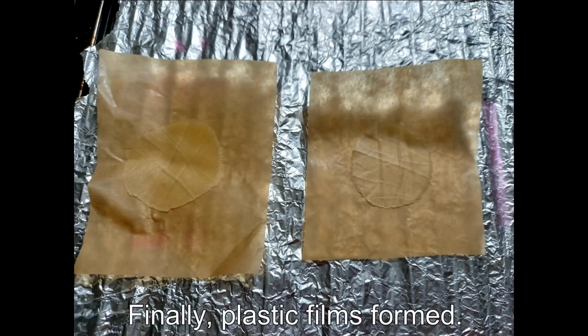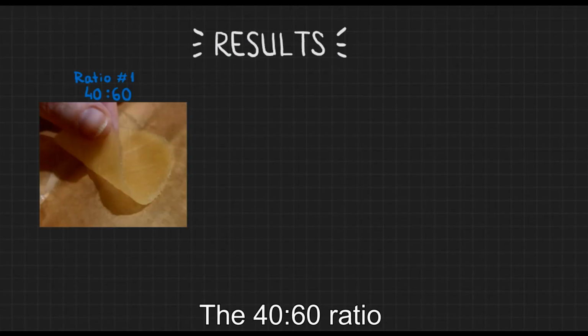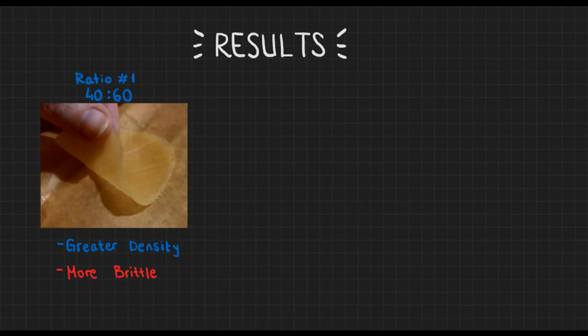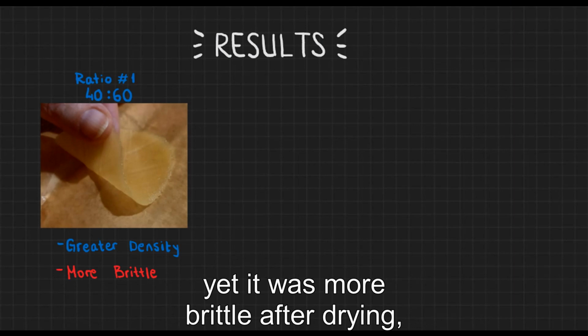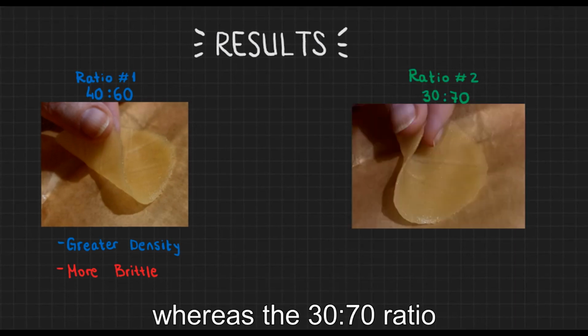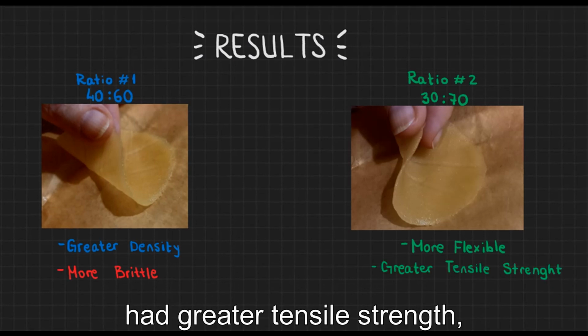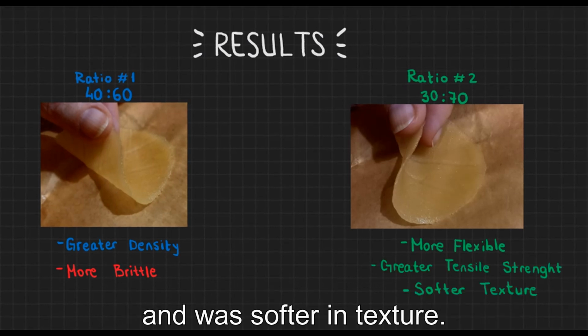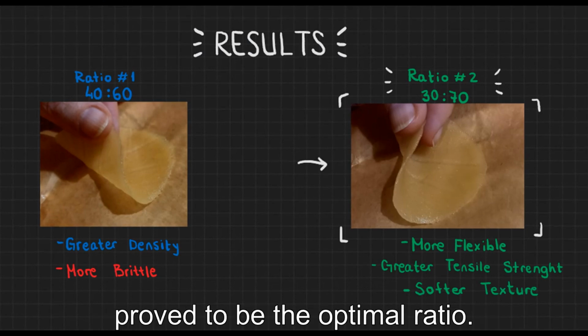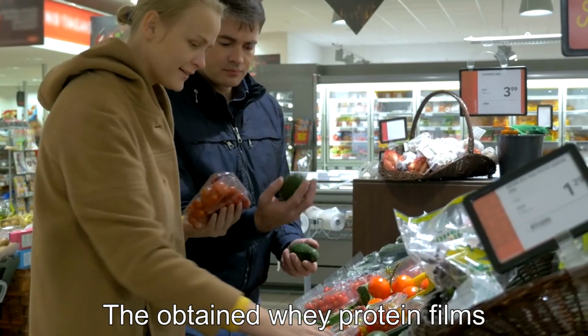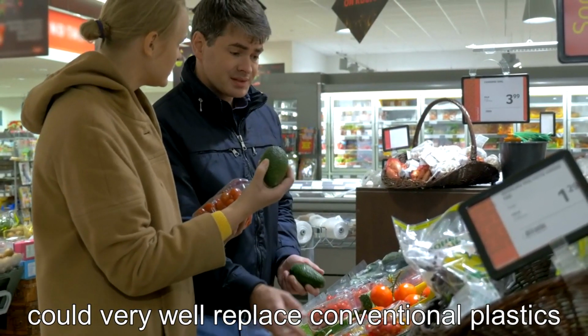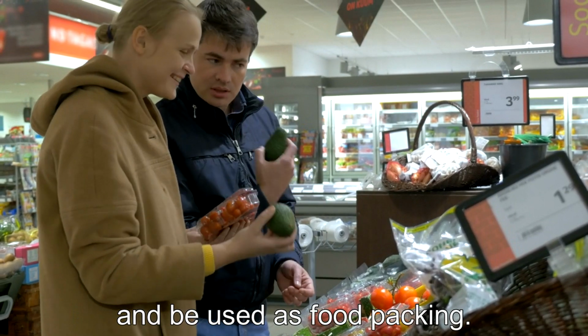Finally, plastic films form. The 40:60 ratio showed greater density, yet it was more brittle after drying, whereas the 30:70 ratio was more flexible, had greater tensile strength, and was softer in texture. Thus, the polymers with protein to PEGMA ratio of 30:70 proved to be the optimal ratio. The obtained whey protein films could very well replace conventional plastics and be used as food packaging.